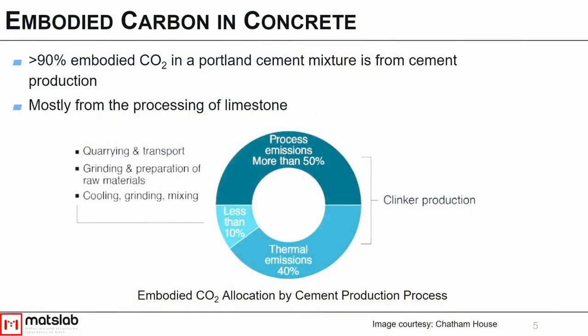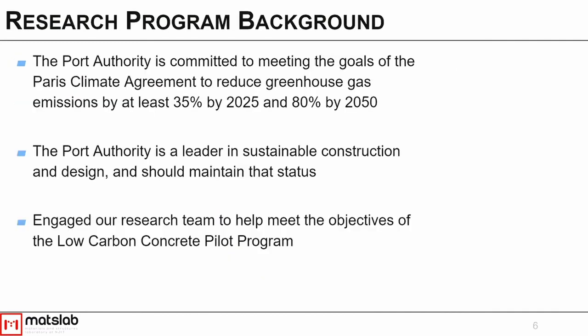Over 90% of it is associated with the production of Portland cement, which is part of the concrete mixture. And when you make Portland cement, you can actually attribute most of the emissions, the carbon emissions, to what we call process emissions, which is part of the chemical changes that happen when you go to take your raw materials and turn them into cement. The rest of the carbon, the other 50%, comes from the process to ship it and grind it, and then the process to heat up your kiln.